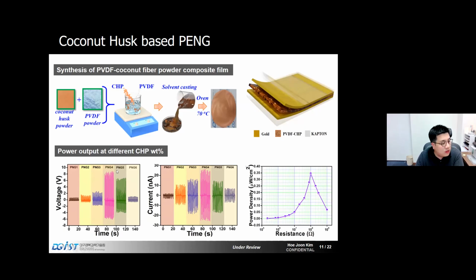The reason for the decrease is that if you put too much powder inside this composite, it becomes brittle. It loses its original polymer softness and mechanical properties, and there is also an uncontrollable accumulation of the powders. We are just grinding them manually, so the powders are not that fine, and I believe that is also another reason.